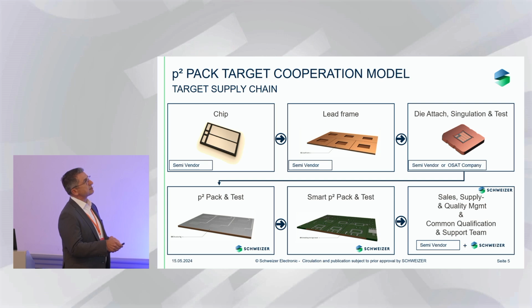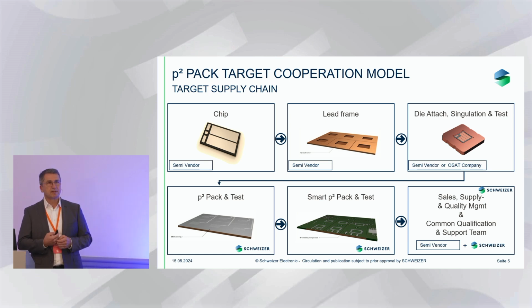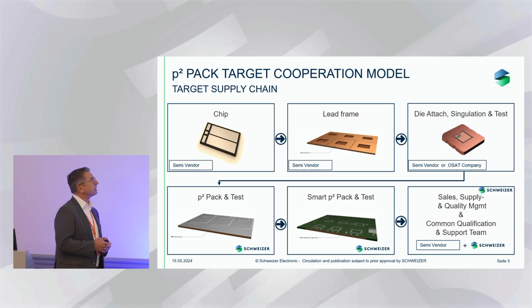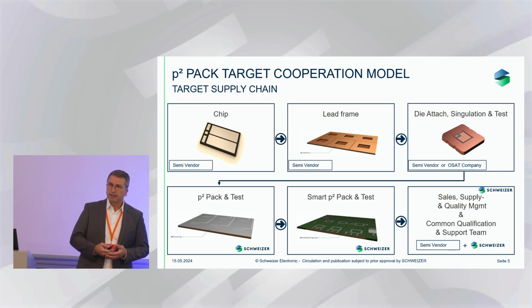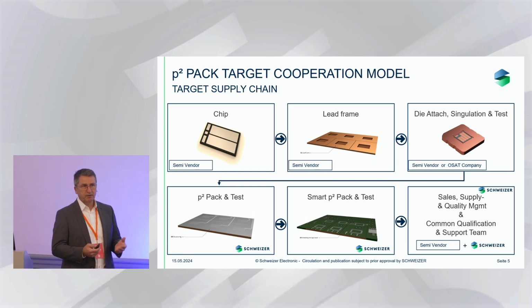And therefore, this test is crucial because we make sure that we work with known good devices or known good standard cells. So we start only with good components into the embedding process. So then we take these components and put them into the PCB, do a lamination process and embed them. That's the power stage. And this power stage is again taken into another PCB, another lamination process where we implement two additional layers on the top side to make it intelligent, the power module. That means you can add the gate drive circuitry or even the full control circuitry and come up with a single board inverter, for example.